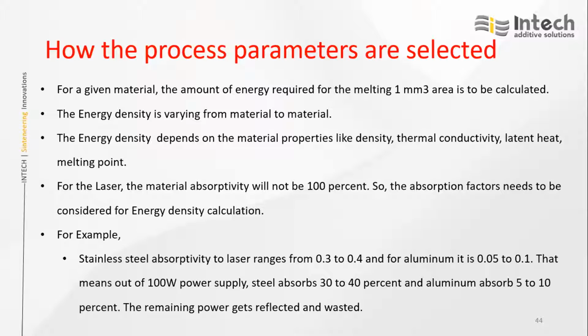Once that is done, since we are using a laser source, it has a certain wavelength, normally the wavelength we are using is 1064 nanometers. At that wavelength, whatever energy we give for a given material, it will not consume all the energy, because the absorption will not be 100%. The absorption factor also needs to be calculated when you decide energy density. If the absorption is 100%, whatever energy density you have calculated, you can directly use.